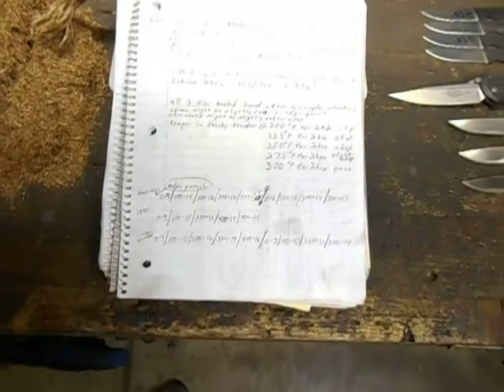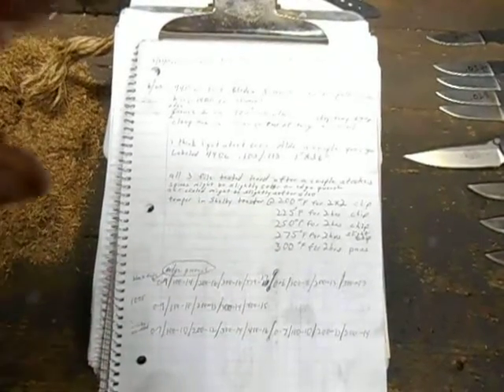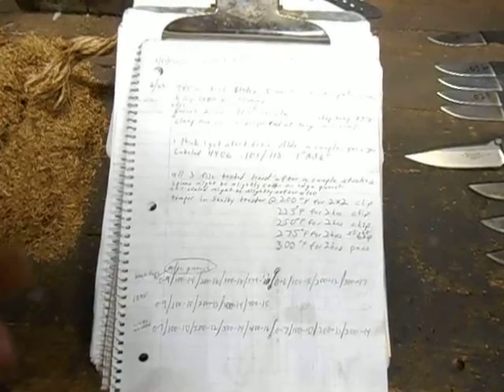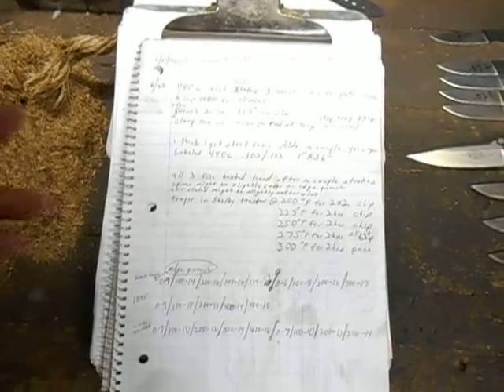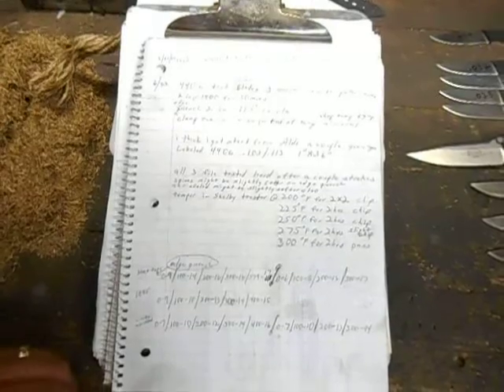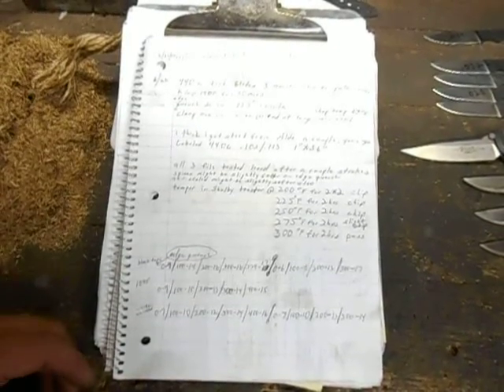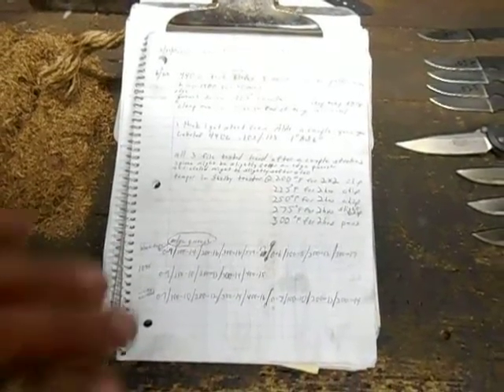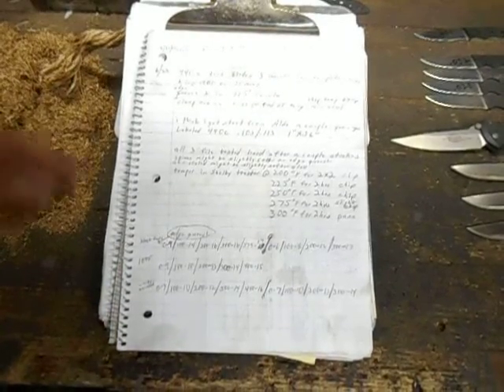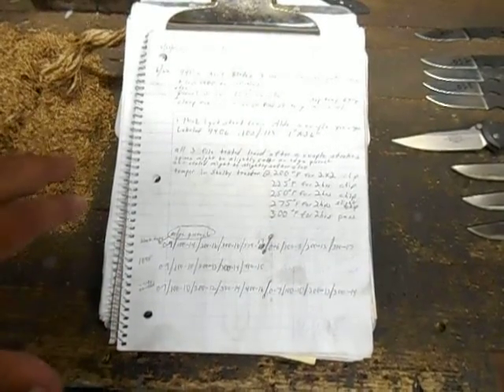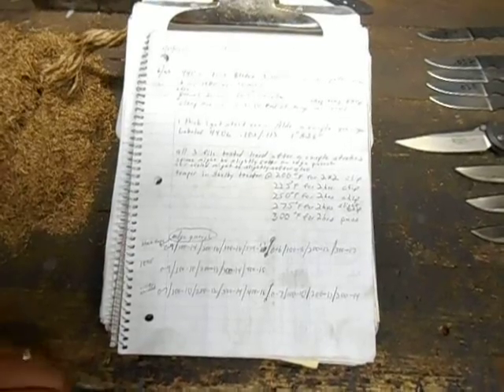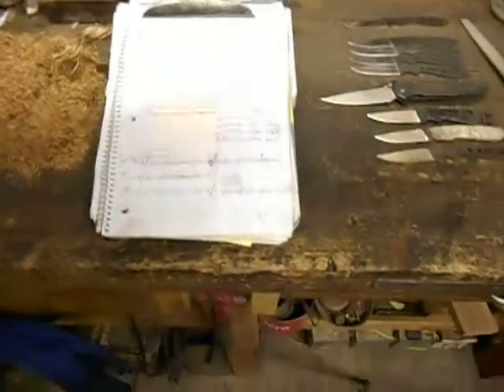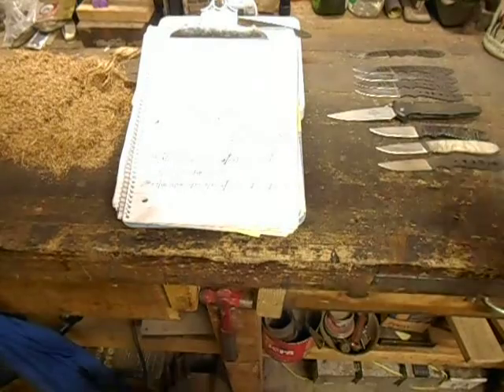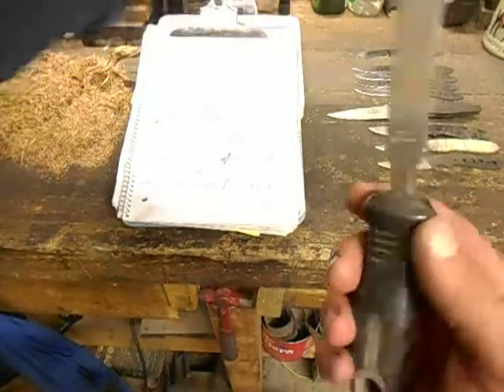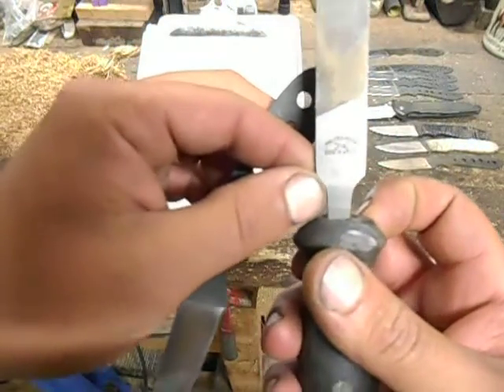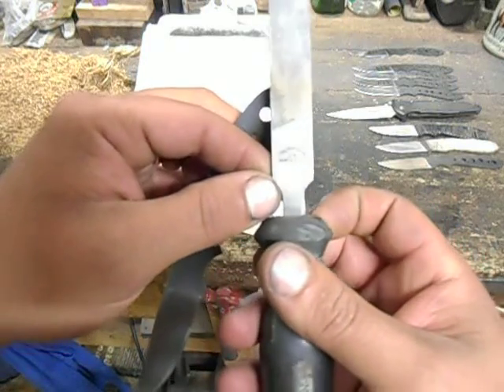So the first couple of strokes with the file will take off any steel that had the carbon burned out of it from being exposed to the hot environment in the kiln. So your first couple of strokes would bite a little bit, and then as soon as that steel got scraped off, the file wouldn't bite anymore. I guess you can do a file test. This is a Nicholson Mill Bastard Black Diamond file made in Mexico.